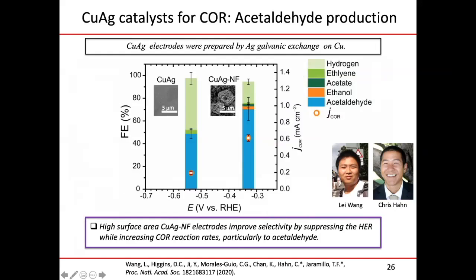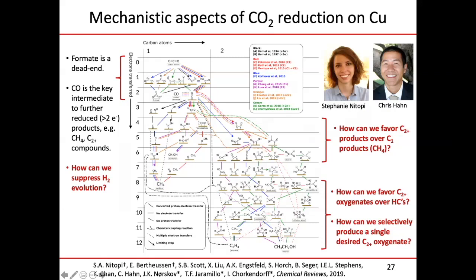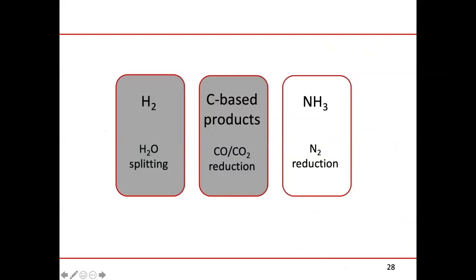We applied this methodology to a copper silver nanoflower morphology, the high surface area. And when you put it all together, you basically get an electrode that steers about 75% of the electricity going to one specific C2 plus oxygenate, which is acetaldehyde. So this is just a way of showing, by engineering the surface of the catalyst, by engineering the morphology of the catalyst, you can actually get through this complex diagram to predominantly a single C2 plus oxygenated species, but we still have a long way to go. Now, if I could have 90 seconds, I will just wrap it up with some thoughts on ammonia.